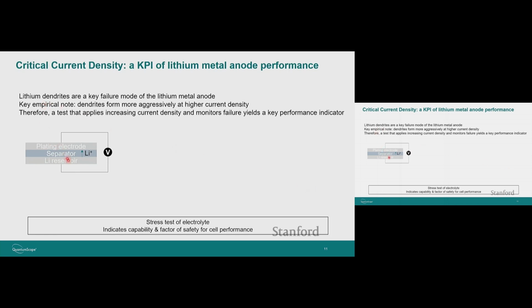The schematic of the test is just you have your solid state electrolyte or separator material. You have one electrode that lithium plates onto and another lithium reservoir that you can use to supply the current density. You hook that up to a voltage supply that'll drive current across the cell, and you turn up the current until you measure a failure. So pretty conceptually simple stress test.